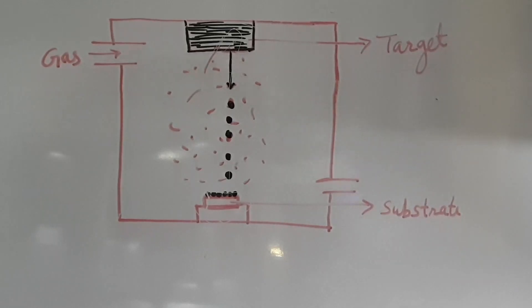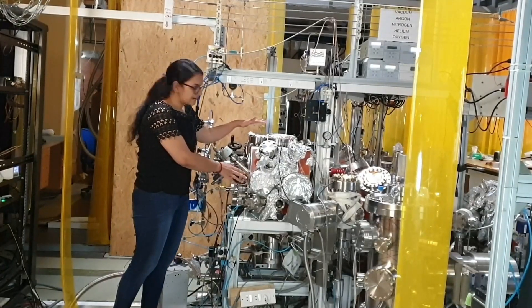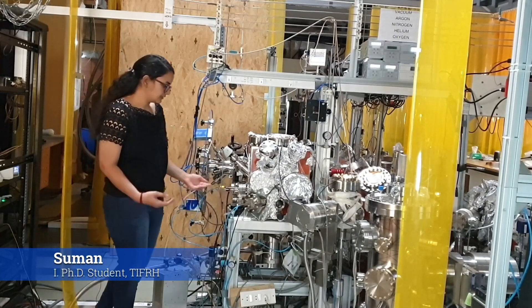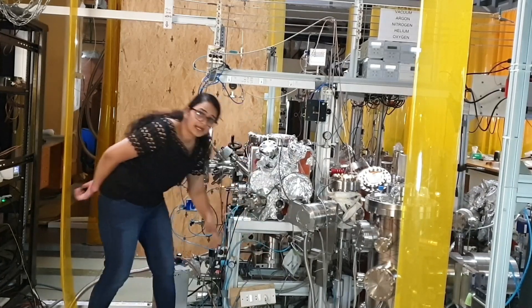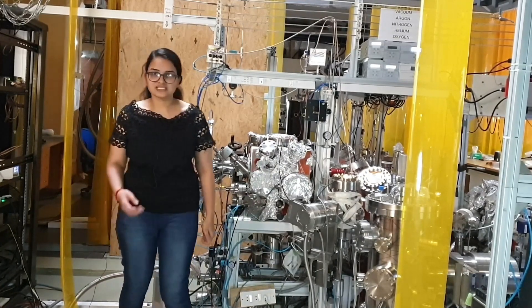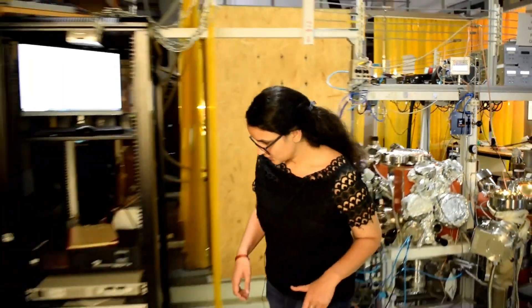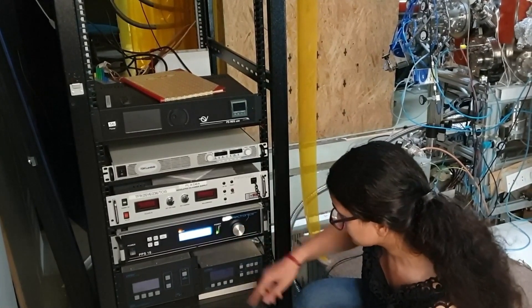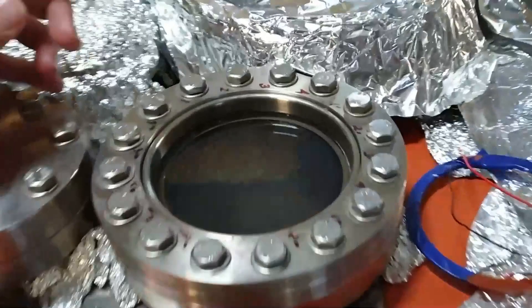Now I will show how these things are done in our actual sputtering chamber. This cubical chamber is our actual sputtering chamber, and these are the gas lines from where the gas is flowed in. These are the turbo pumps for vacuum creation. I have already mounted the substrate and maintained the argon flow — now we just switch on the power supply and create the plasma. You can see the current — around 123 milliamps — and this purplish color inside is the plasma.